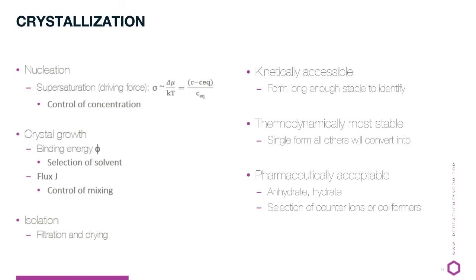Polymorphism is the result of the kinetically first accessible form being preferred to crystallize above the thermodynamically most stable one. So kinetically says what can you make, thermodynamically is what you want to have. Otherwise also the pharmaceutically acceptable forms, looking at an anhydrate or hydrated form, as well as a selection of suitable counterions or coformers. All is controlled by the nucleation, and the final properties of your material are decided by the